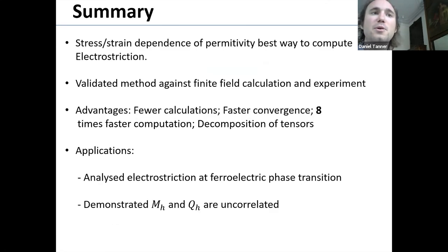So to summarize, we showed that the stress strain dependence of the permittivity is the most efficient way to calculate electrostriction and most useful. We validated the method. We demonstrated it had advantages of fewer calculations, faster convergence, faster computation time for a given set of parameters, and allows more insight into electrostriction by the decomposition of the tensors. And I showed two applications. Thank you. Well, thank you very much. You're perfectly on time.